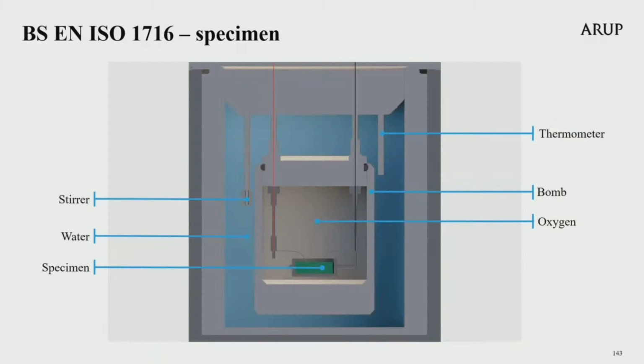The bomb is a watertight vessel and contains pure oxygen. The bomb is contained within a larger enclosure which is filled with water. When the specimen is burnt in the inner watertight vessel, it releases heat which is transferred through the walls of the vessel into the water surrounding it, and in doing so heats up the water. The increase in water temperature is measured using a thermometer, and a stirrer driven by a constant speed motor is placed in the calorimeter.